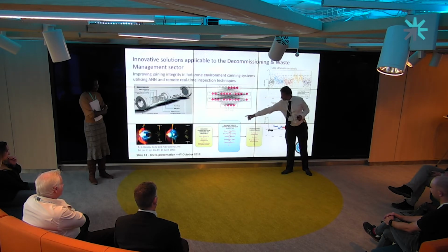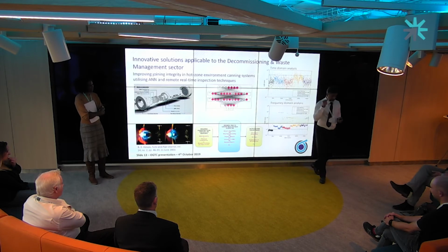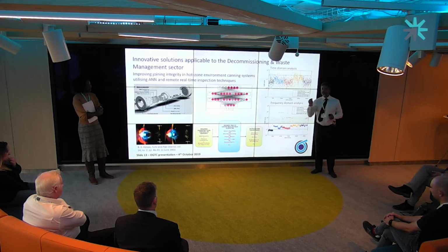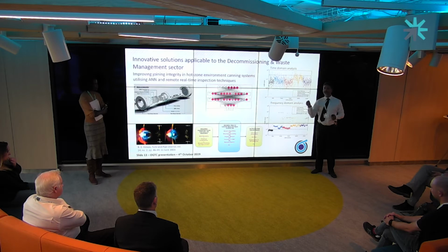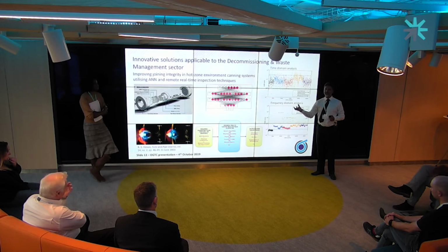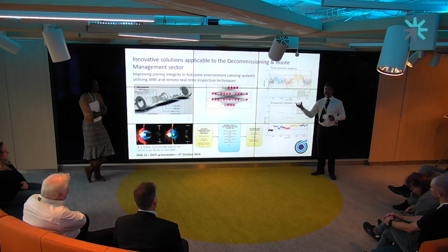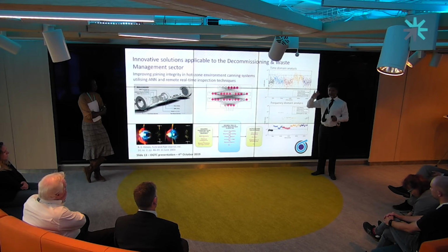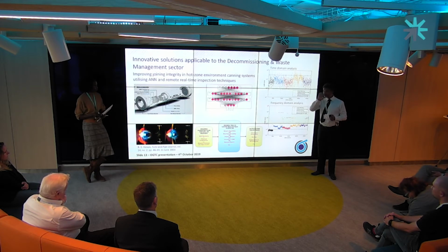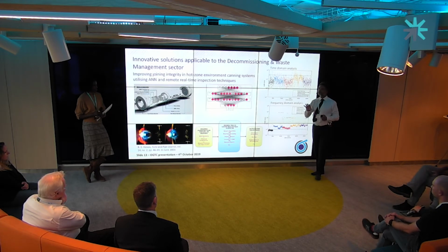The thing here is very important, because a major failure could have occurred in one of their aero engines, sorry, faux pas there, on fuel lines. And it was to do with austenitic stainless steels. And the sad thing about it is that the material was changed because it went to a global specification. And what's really important there is that the specification was within standard, but if you know anything about welding these materials, they can cause solidification cracking.